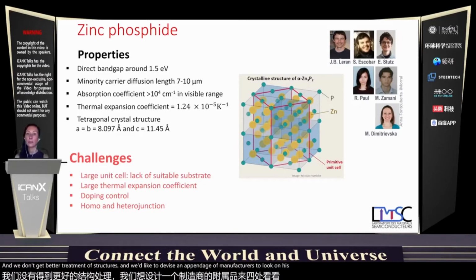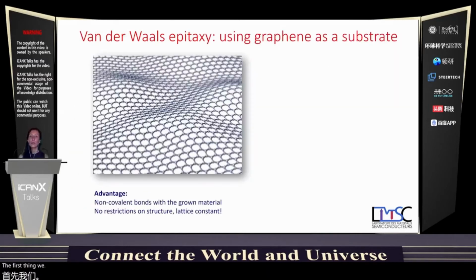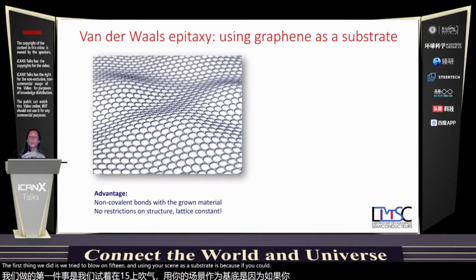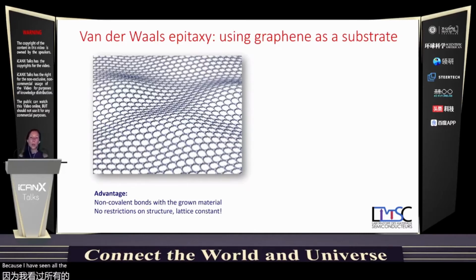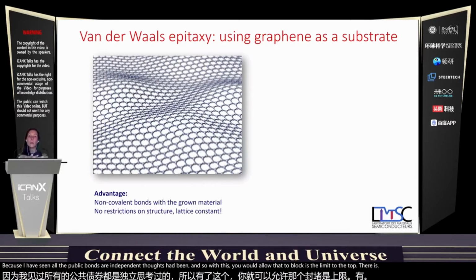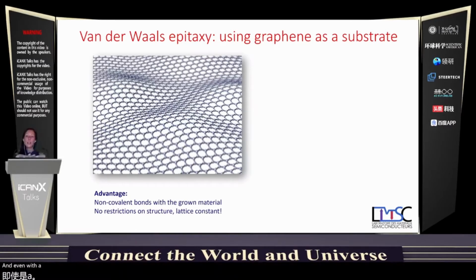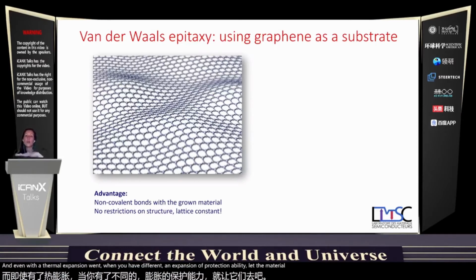on this. The first thing we did is we tried to grow on graphene. We use graphene as a substrate because if you grow anything on top, you will not have any covalent bond with the graphene, because in graphene, all the covalent bonds are in the plane and not outside the plane. And so with this, you can grow a crystalline material on top. There is no lattice mismatch. And even with the thermal expansion, when you have different expansion or contraction, the material just floats on top of it. So you will not create any cracks.